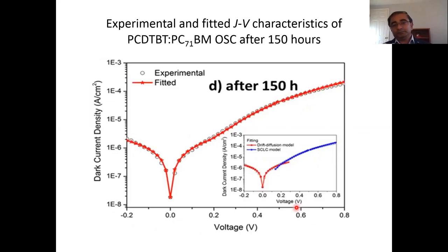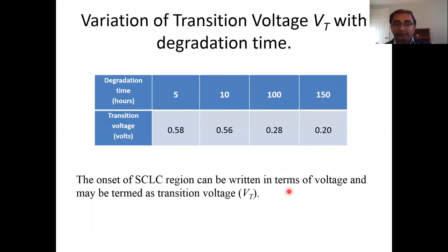So the degradation phenomena of organic solar cells can be understood with the help of two models. One is called the drift diffusion model, and the second one is called the space charge limited current model. And the transition from drift diffusion to space charge limited current model happens at what is called the transition voltage. This transition voltage is very important, because it depends upon the time of degradation. So you can see from here, for different times of degradation, you have a different transition voltage.